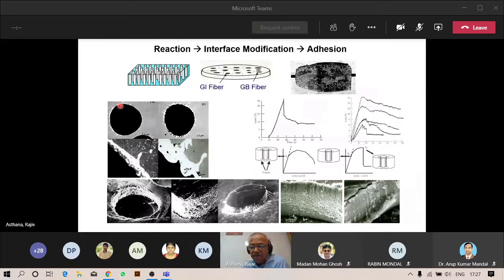So this is a kind of roughened behavior. The interesting thing here is that reaction can increase the bond strength dramatically, but that may not be very beneficial, especially because the fiber itself is heavily degraded. So the composite properties will not improve even though the bond strength has improved. So the idea is that you can modify the interface in different ways to control the bonding or the adhesion.